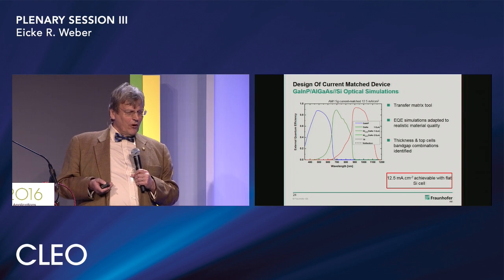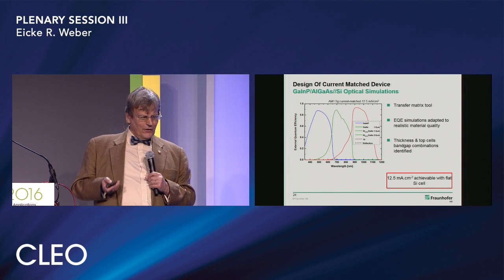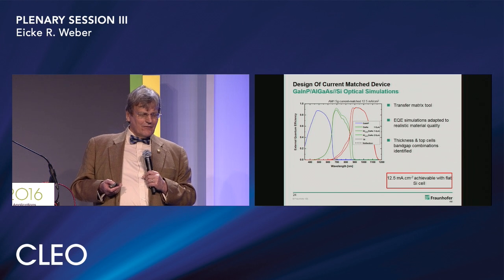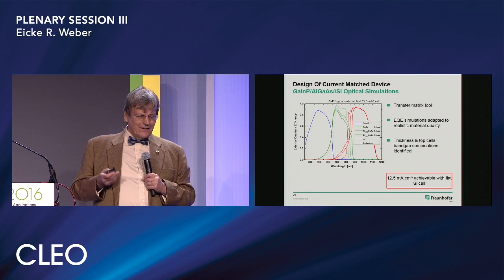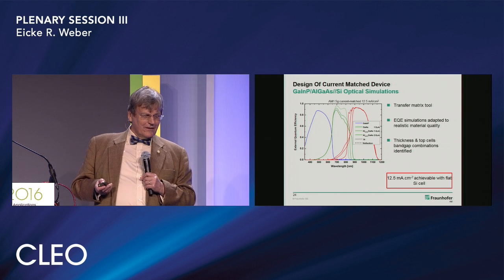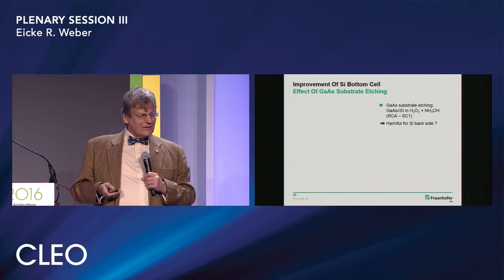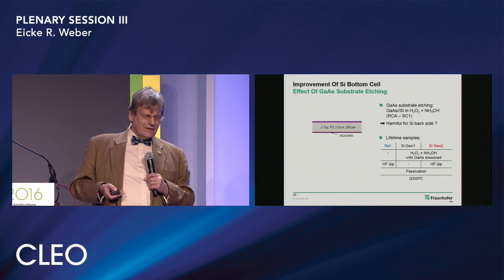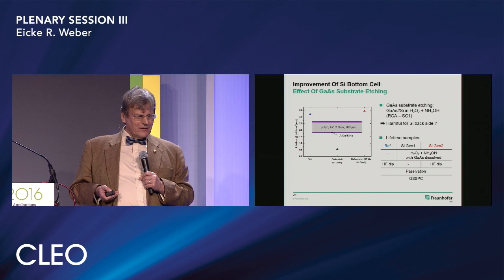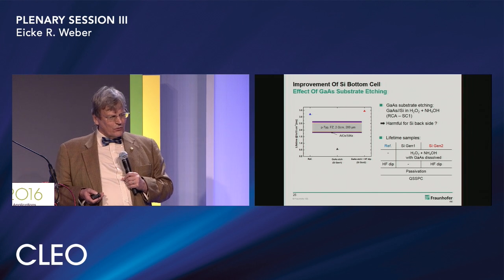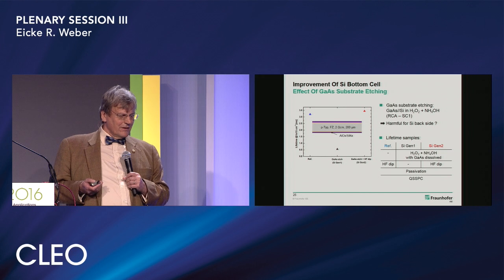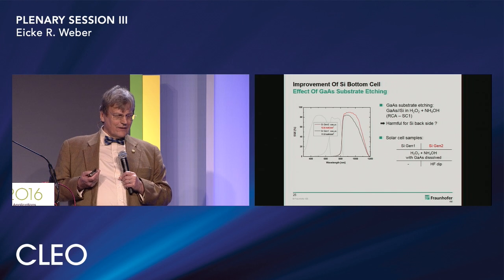So then, of course, come the optical simulations. This was a first step in such an optimization, and then by adjusting the structure, one can get more and more out of it, increase the efficiency in order to reach the best possible result on such a crystalline silicon solar cell. And one has as well to make tricks with technology, substrate etching. This is described here. As you see, it shows how we can improve the carrier lifetimes, and this, of course, is at the end the key factor for the solar cell efficiency.